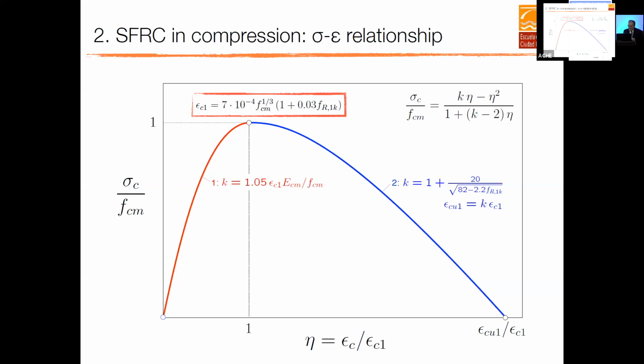And then a particular thing that has to be carefully observed is that the equation has a parameter K, and this parameter K has one value in the ramp-up curve that depends on the elastic modulus, and another one in the softening part, which depends, again, on this residual flexural strength. So this very simple equation is what we have seen in this orange curve.